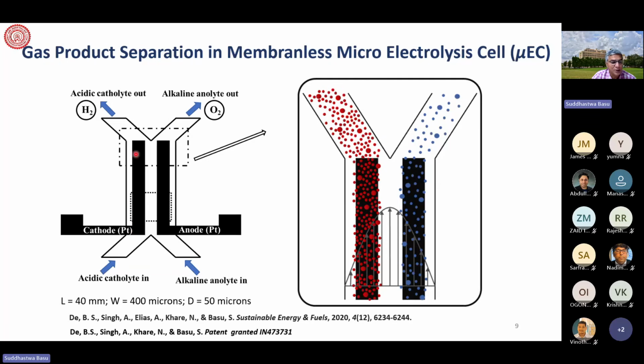So what it is is that we are using a microfluidic channel, having a platinum anode in one channel, or two arms as a Y-shaped arm together. One cathode is platinum and the anode is platinum, and we use alkaline anolyte and acid catholyte, and actually this is an asymmetric electrolyte. So what EPFL did is use either alkaline or acid electrolyte, but we showed that when we use acidic catholyte and alkaline anolyte, because of the liquid junction potential in a favorable position, because we have a difference in pH between the acid and alkali, which gives rise to a liquid junction potential, we can use this liquid junction potential favorably between this interface,